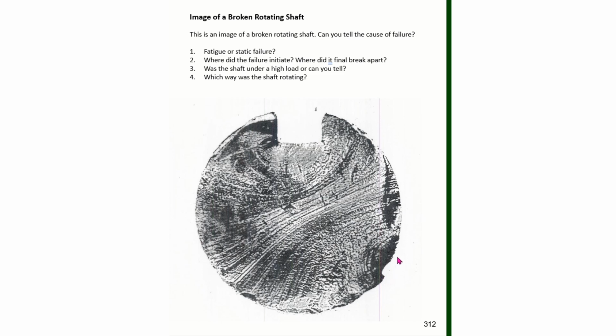Now we know the crack didn't initiate here because this is a nice smooth surface and there wouldn't be a crack in this region. But up here in this notch where we have this sharp corner, that's where a crack would initiate. That sharp corner in that notch is almost a crack to begin with, and then it propagates and comes this way.